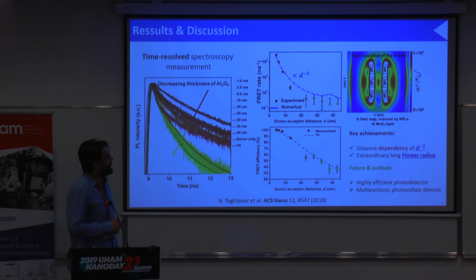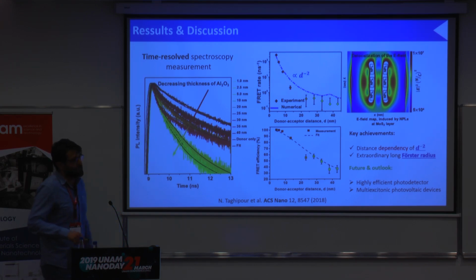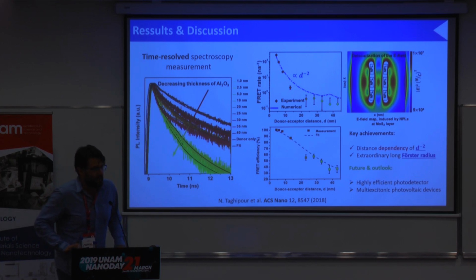As you see here, below 10 nanometers we achieve ultra-fast energy transfer, which to the best of our knowledge is the fastest one, and it reached up to 268 per nanosecond of transferring the excitons or carriers from our donor to the acceptor. Also, below 8 nanometers, we achieved a remarkable near-unity transfer of excitons or carriers from our donor to the acceptor.